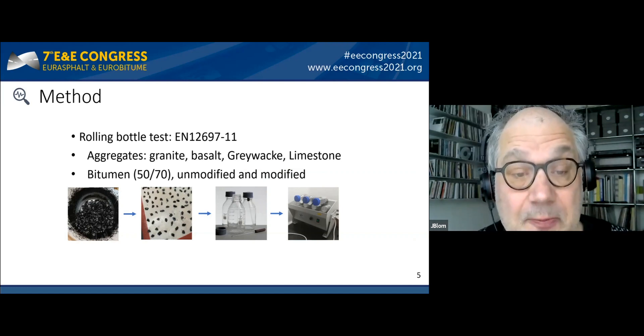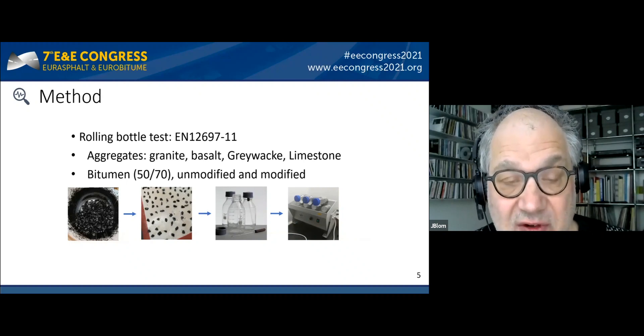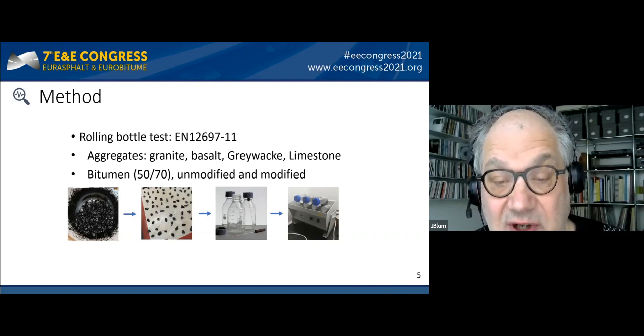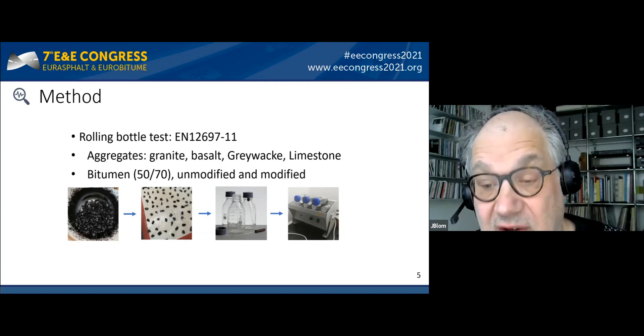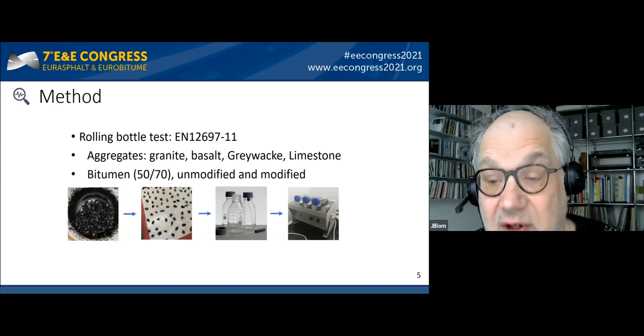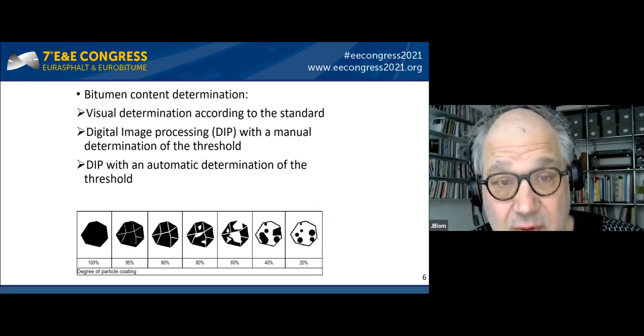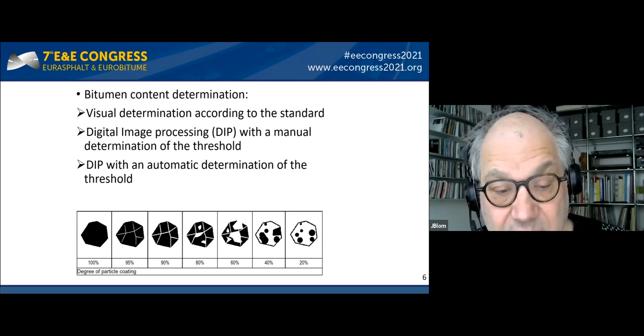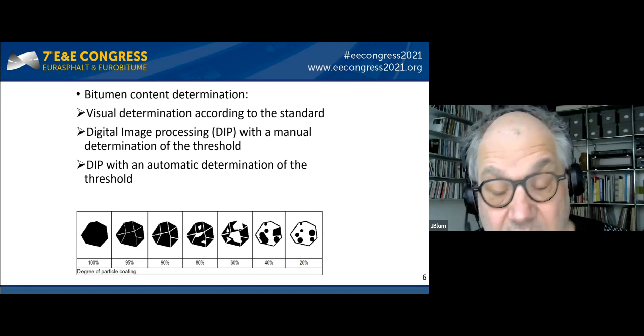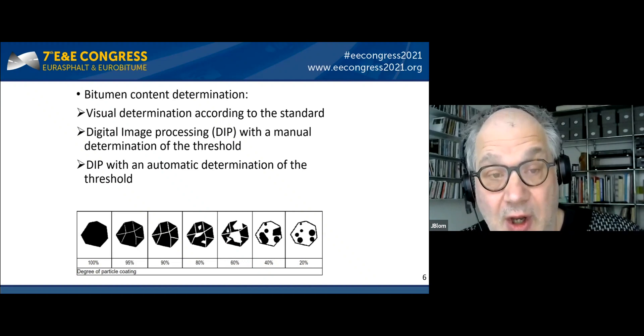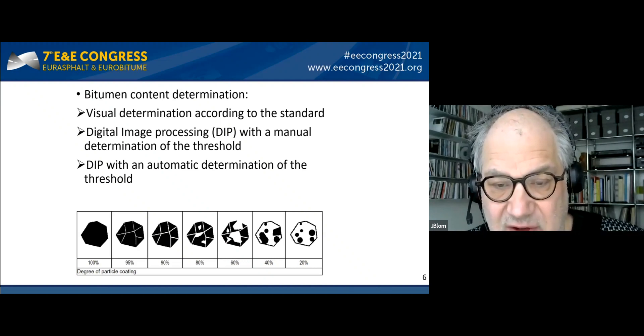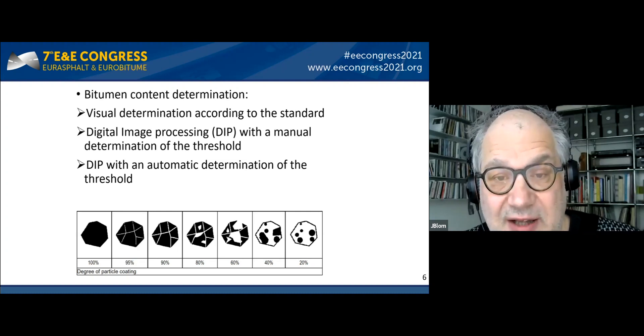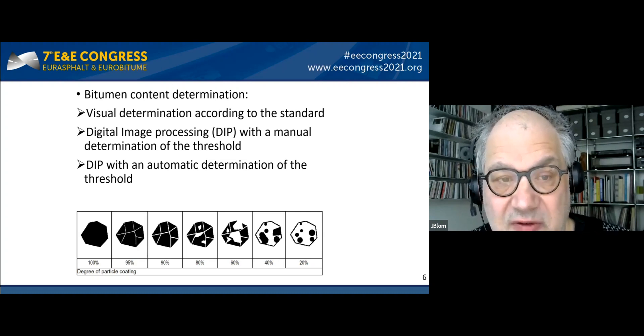In the European standard there is a method to examine the affinity of bitumen to stones: the rolling bottle test. The test is quite simple: you coat your stones with bitumen, separate them to avoid clusters, put them into special bottles with water, and place them on the rolling bottle machine for a time defined in the Euro code. Afterwards you do a visual inspection, comparing the stones with degree-of-particle-coating reference images — but this is a very subjective method, highly dependent on the training of the observer, and can lead to large variation in observations.